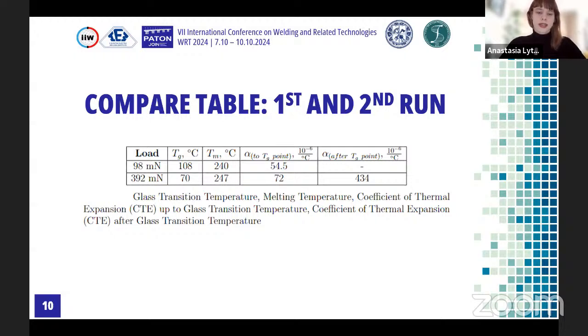Here we can see the results for glass transition temperature, melting temperature, and coefficient of thermal expansion up to the glass transition temperature and after the glass transition temperature. We can see that the coefficient of thermal expansion after the glass transition temperature is much higher than up to the glass transition temperature because we released internal stresses and relaxed these residual stresses as I described before. The melting temperature is in approximately the same range, and we can see the glass transition temperature is also approximately in the same range, but because we use a different method, it can vary.